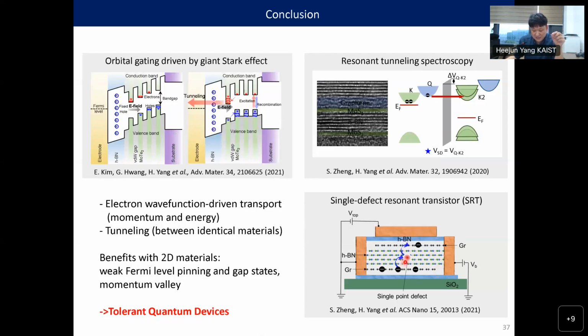Good question. As I mentioned, for Landau levels, for example, the charge puddle effect, when we make some quantum transport, we need a very low temperature and a very high magnetic field. We have some level broadening and we have to separate the levels by enough energy. But if we use a very local single defect, one example is this single defect resonant transistor, we can probe only a certain area of the graphene. So thanks to this local single defect state in the hBN, we can make more tolerant quantum devices. Tolerant means we can avoid the charge puddle effect, so we can avoid the level broadening effect and we can measure it at room temperature, hopefully. So this is one example.